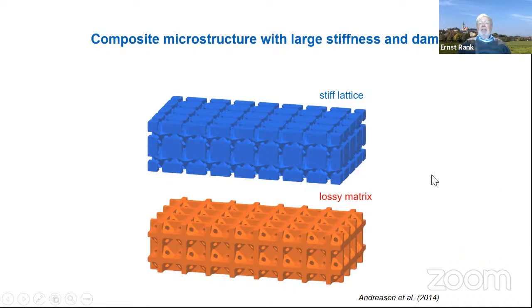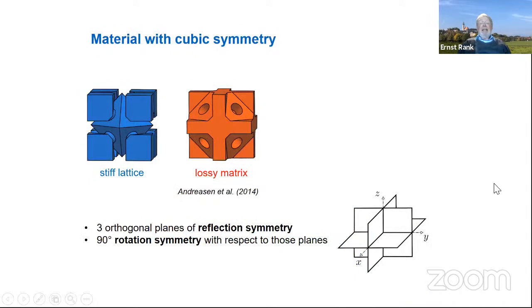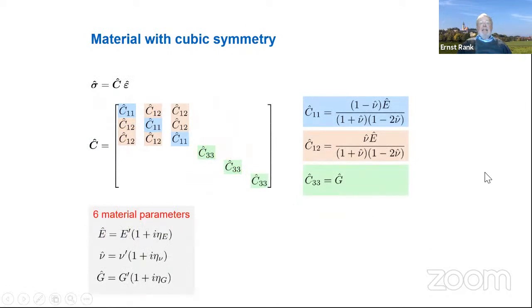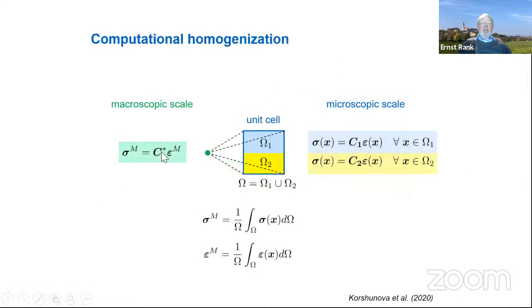Well, if you look to this, then the stiff lattice is something which is in a sense ideal to be manufactured by AM. The lossy matrix is then just filled in, and the structure which we are using is one which was defined by Andreasen and Sigmund in a publication in 2014 by topology optimization. Essentially, they got it in this way. And the material of the combined structure is something which is composed, well, in the microscopic scale out of these two types of structures which we are having.